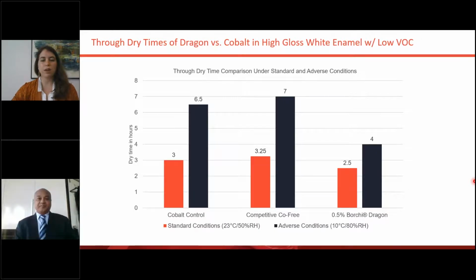This is with our Borchi Dragon technology, again under adverse conditions—our standard lab adverse conditions. We test at cold temperature, very high humidity: 10°C and 80% humidity. Compared to competitive cobalt-free options as well as a cobalt carboxylate control, Borchi Dragon shows very similar dry time, so a lowered impact on that adverse condition curing.